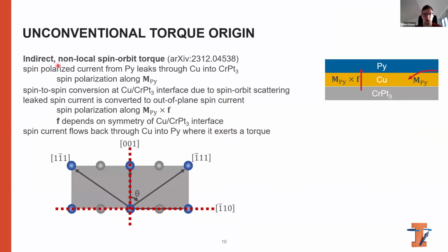So they say that the indirect non-local spin-orbit torque mechanism is responsible for this, and there's actually an archive paper by them specifically for this indirect non-local spin-orbit torque that doesn't involve unconventional torques, but it explains a similar mechanism. So the way that this works is that the spin polarized current from permalloy leaks through the copper into the chromium platinum 3, which I just indicate here.